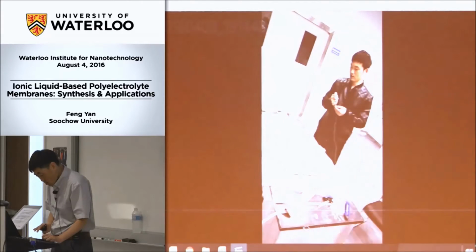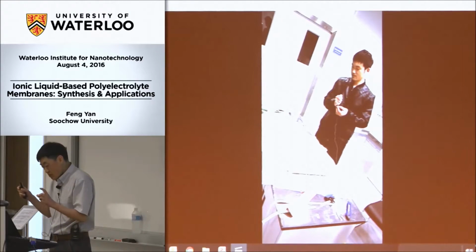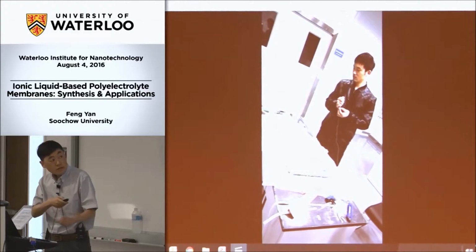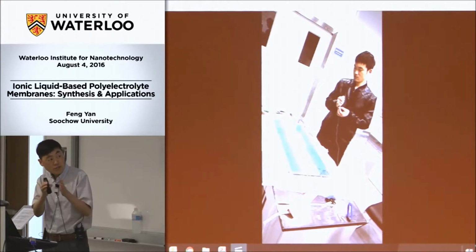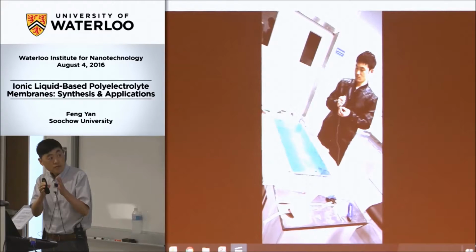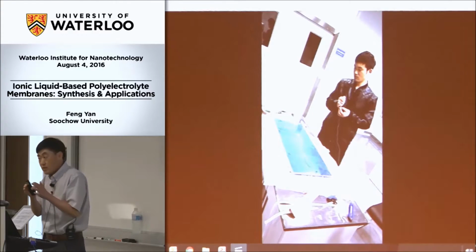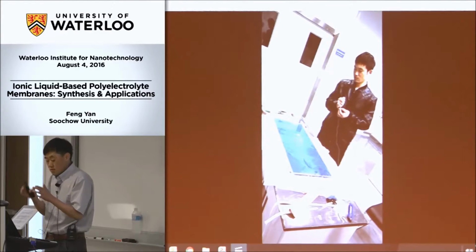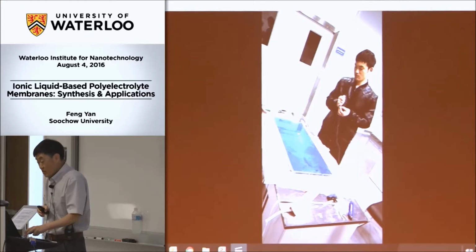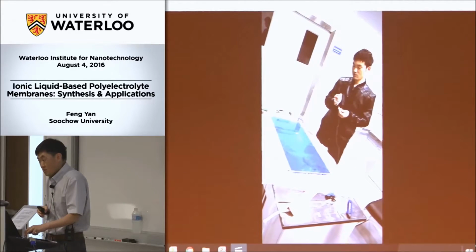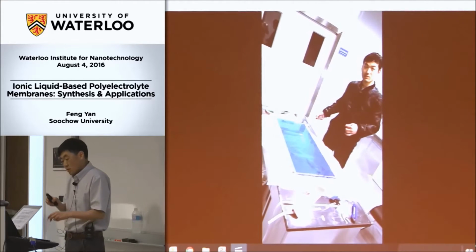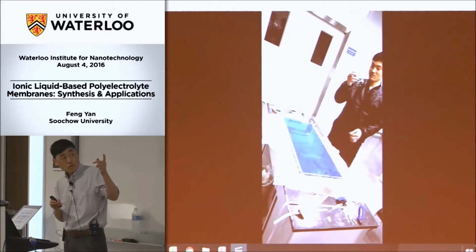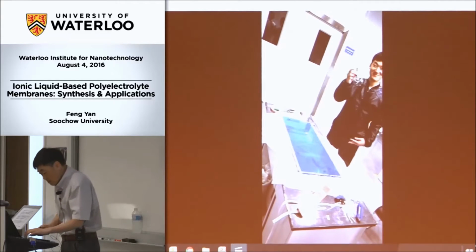And you just need to use 2 batteries. And you can see this is a really large window, and the color changes little by little. And the time is roughly around 15 seconds. I think it's acceptable for real applications. Yeah, and the voltage you need is two batteries.